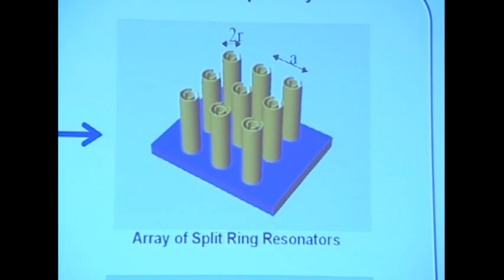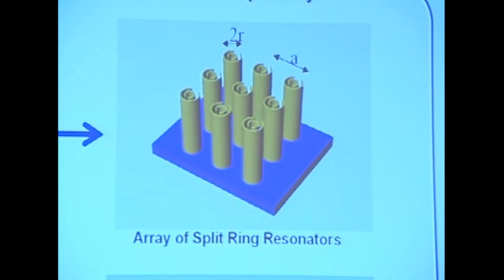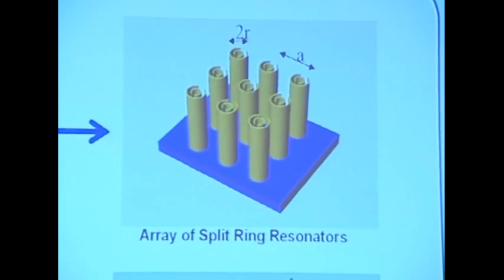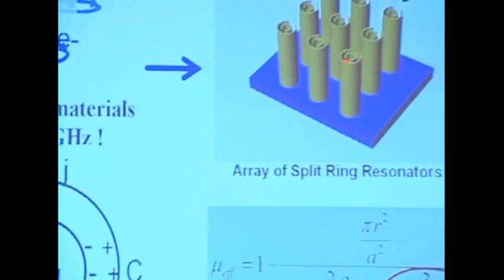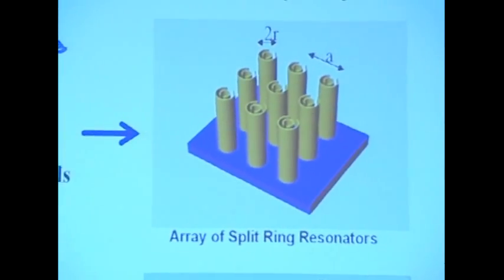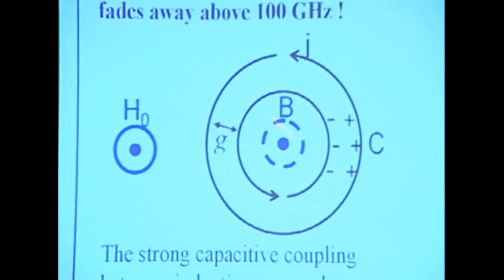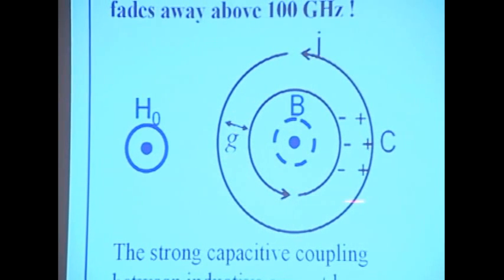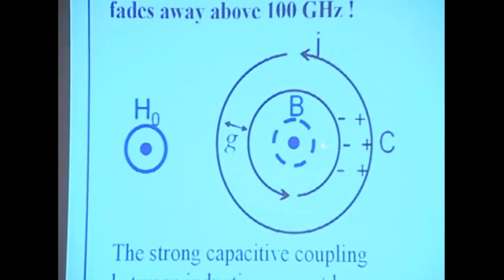This can be constructed by metal, for example. Itself doesn't have magnetic response at this high frequency. But as you can see, in this top view of each cylinder, if you excite this entity with an external magnetic field, that field will immediately induce a current around the metal loop. At the same time, these two form a capacitance between the two layers of the cylinders, right? So you have inductance and capacitance, and that leads to the so-called LC circuit, or a resonance.